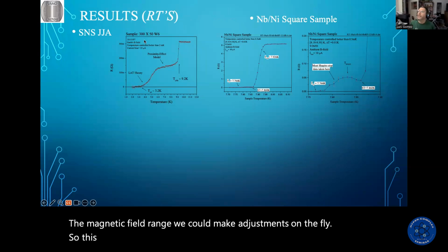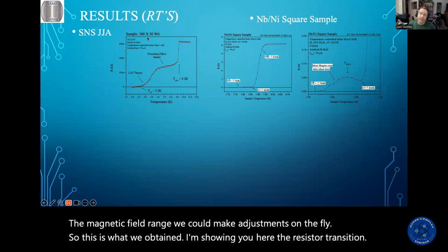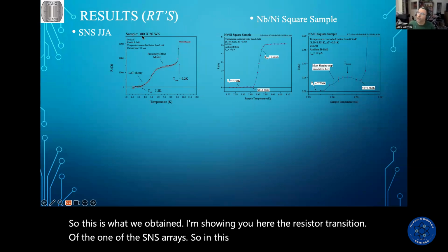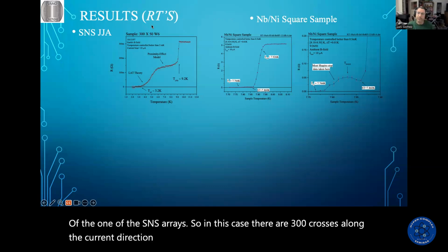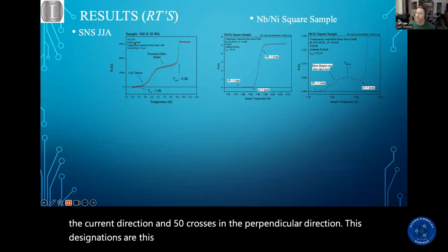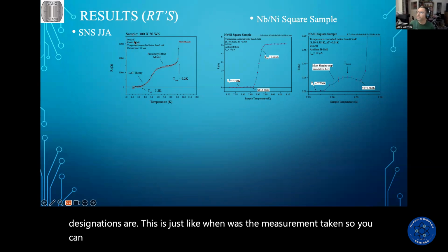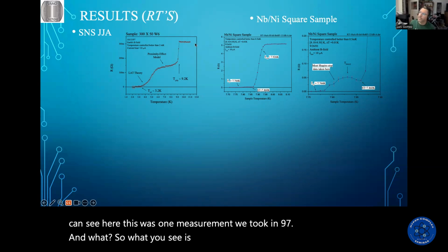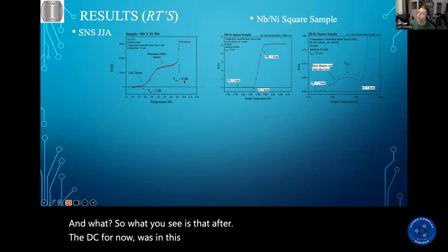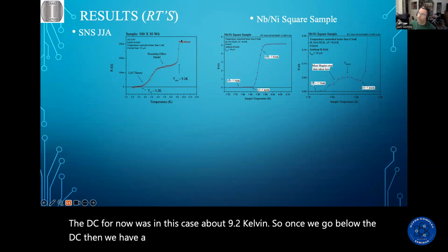So this is what we obtained. I'm showing you here the resistive transition of one of the S-N-S arrays. In this case, there are 300 crosses along the current direction and 50 crosses in the perpendicular direction. These designations just indicate when the measurement was taken — this one was taken in '97. What you see is that the TC for niobium in this case was about 9.2 kelvins. Once we go below the TC, we have a rapid reduction of the resistivity.